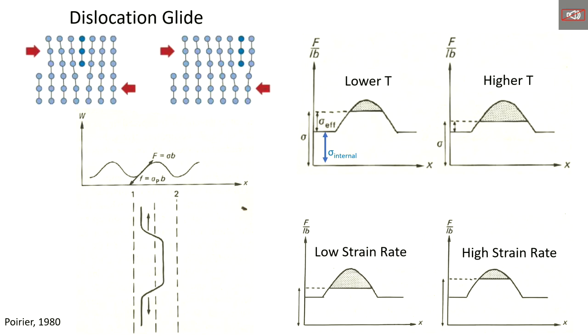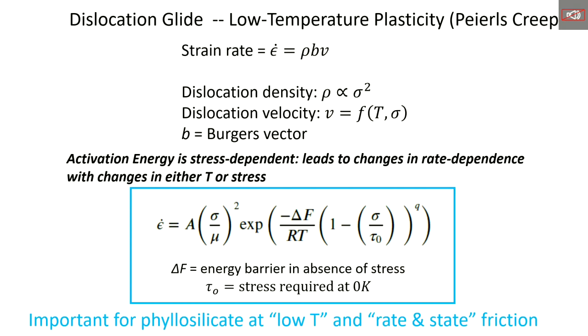The same is true with strain rate, right? If you have a very low strain rate, you have a greater probability of some vibrations leading to the ability of the dislocation to move along to its next lattice position. So that process doesn't seem that complicated, but what it does lead to is an activation energy that's both dependent on temperature and stress. And that gives you this funky exponential with all this extra stuff in here. But really, that's just an explanation for that energy barrier.